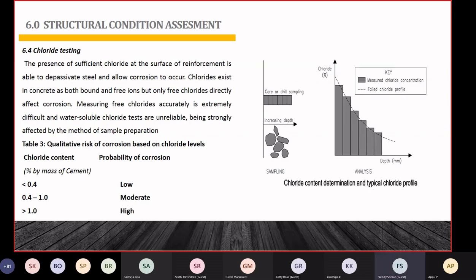This I mentioned to you earlier also, chloride testing. After the chloride testing, we can find out the chloride content. From the chloride content, we can say that if it is less than 0.4, the probability of corrosion is low. If it is 0.4 to 1, percentage by mass of cement, it is moderate, and more than 1, it is a high chance of corrosion. This is chloride testing. Again, this is one assumption.